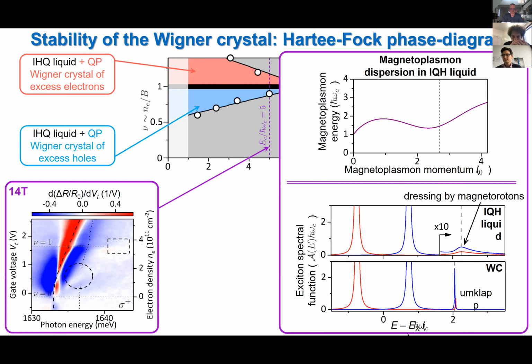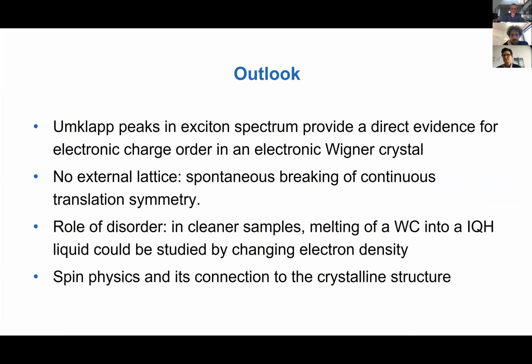Okay, so much more has to be done. We need to look at higher quality samples, hopefully correlate with transport measurements, but we believe that what we see here is really the first direct evidence for the charge order that appears in a Wigner crystal, where we do not have an external potential and the crystallization occurs spontaneously. Okay, so I already made the first point. So actually, I made all the points.